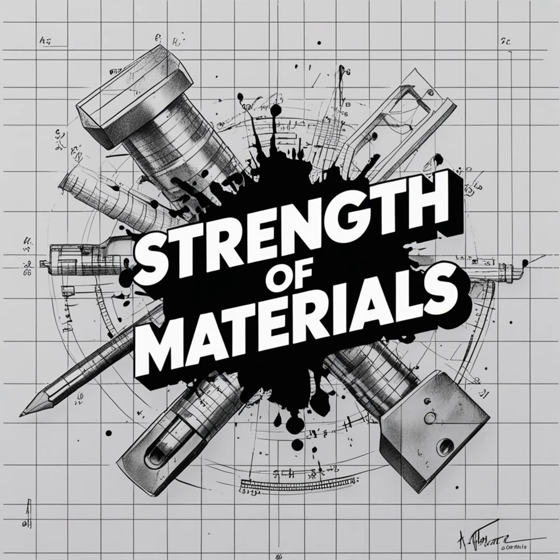I see. A crack physically concentrates the stress right at its impossibly sharp tip, so the damage accelerates rapidly. In this high-low scenario, the part will fail much earlier than Palmgren-Miner predicts. The sum of the fractions might only reach 0.7 before the part snaps. So the math says you have 30% life left, but the part is already broken on the floor. That's terrifying. Now let's reverse it.